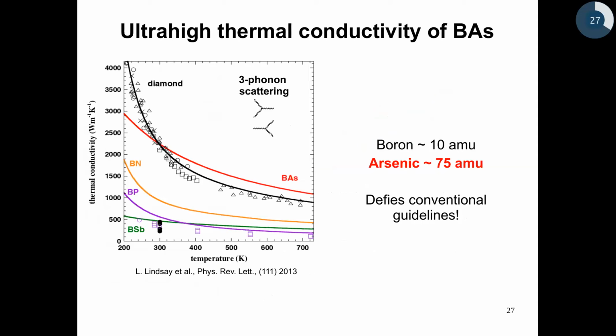But as a surprise, in 2013, when Lindsay and co-workers did the calculations for several materials, they found out that their prediction using this conventional approach, that is with 3 phonon theory, showed that the thermal conductivity of boron arsenide can actually exceed that of diamond beyond room temperature. Notice that boron arsenide has almost 3 times higher average mass than that of diamond. So it is a heavier material than diamond, therefore defying conventional guidelines that I presented earlier in the previous slide. Yet their calculations using 3 phonon theory, the conventional theory, predicted that the thermal conductivity could be higher than that of diamond.